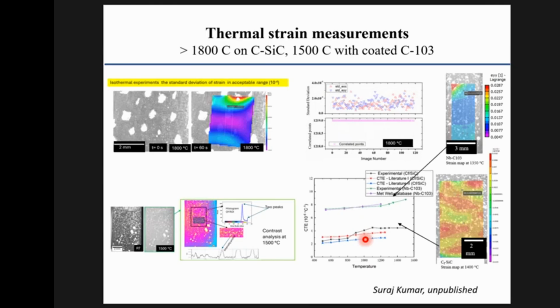This one is at least 1800. It's probably higher because some thermocouple made of platinum melted along the way. So the student was conservative in saying it's at least 1800, but it's probably around 1900 to 1950. With niobium, of course, you can't go that high. These measurements are made at 1500 degrees. So the strain measurement capability is there.